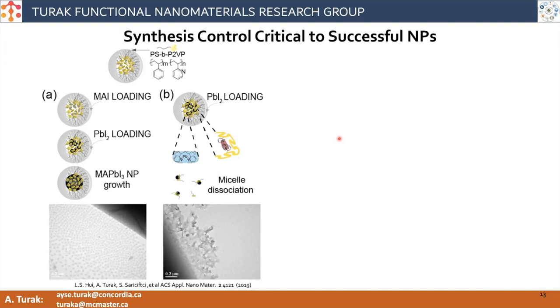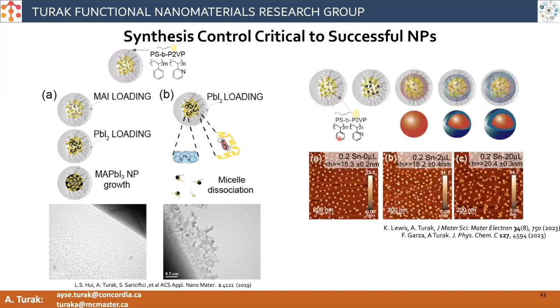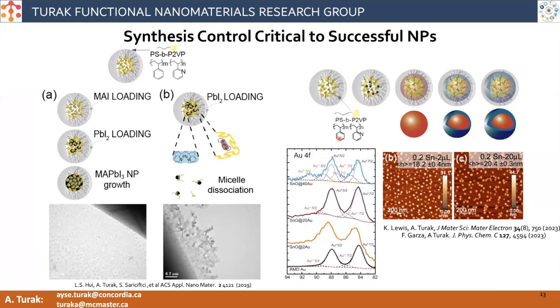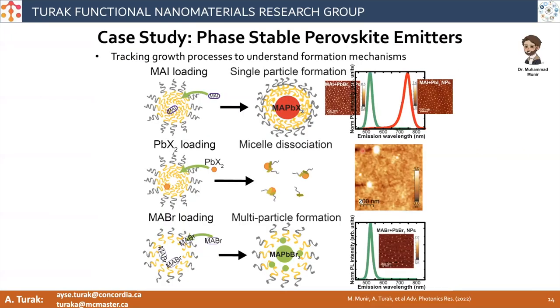If you pick the wrong order, and in this case you use the metal halide rather than the organic component first, you end up with a structure where the micelle falls apart, and you get nothing, right? So you have to be very careful about how you're approaching your synthesis. Another example, if you're going to make some of these core-shell type structures, it's powerful. You can make different thicknesses of the shell by adjusting the various parameters. And that also gives you access to new states of matter. For example, by virtue of having a gold shell forming over an oxide, you start to see these new gold oxide states that aren't possible without that support.